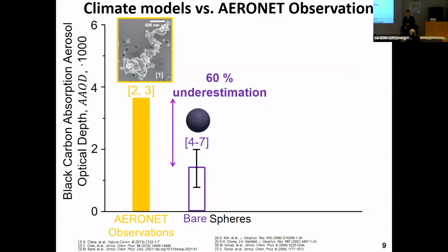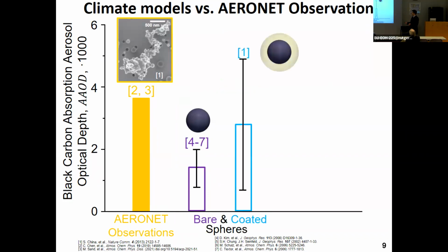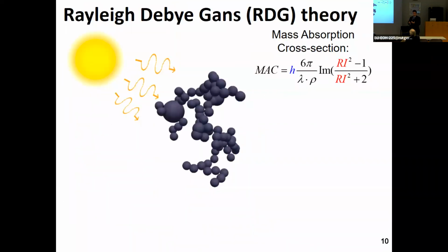Now, of course, the most recent models that were published just earlier this year in the newer IPCC account for the coating. The coating in general enhances the light absorption of these nanoparticles through the so-called lensing effect. If you have questions, I can explain more in the Q&A. So the difference between the observations and the models was reduced. But you can see over here that we still had about 20% underestimation of the real light absorption by black carbon. So this still tells us that the contribution of black carbon to global warming is still underestimated by global climate models. So this is what we try to do to account for this.